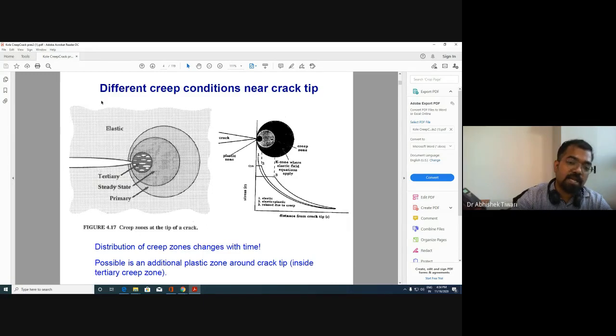Now, keeping this in mind, once we have a crack in the system and we have applied some stress on it, the strain at the very tip is going to be much larger than the strain in the remote areas. This we have understood in our elastic plastic fracture mechanics lecture, that the remote area deforms elastically and you have a plastic zone at the crack tip, right? Similarly, in creep, you will have a creep zone.